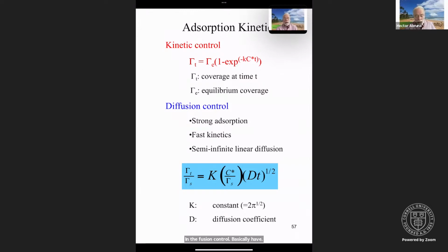And so in this context, for kinetic control, you can look at the coverage as a function of time. So gamma sub t is gamma equilibrium, meaning what the equilibrium coverage is under the experimental conditions, times 1 minus e to the minus k concentration t. And so this is exponentially dependent on time. So when you're kinetically controlled, the increase in surface coverage will be exponentially dependent on the time, concentration, and the kinetics.